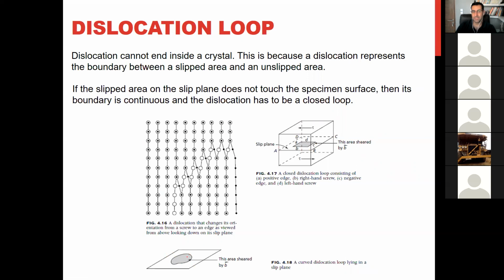When you have a loop, it means this part is deformed and around it is not deformed. If, for example, this is the slip plane and this is the Burgers vector of this dislocation, then this part of the dislocation is edge, and these parts are screw dislocation. So a dislocation loop always consists of screw and edge dislocation, depending on the direction of the Burgers vector. This part is, for example, screw, and this part is edge dislocation. And this part is a mix of both, when we have a transition from screw to edge.